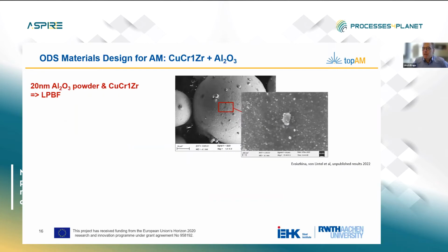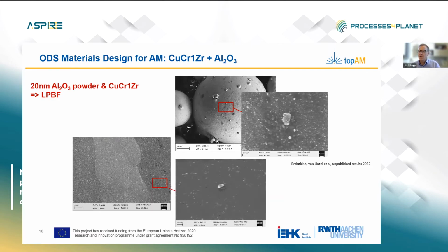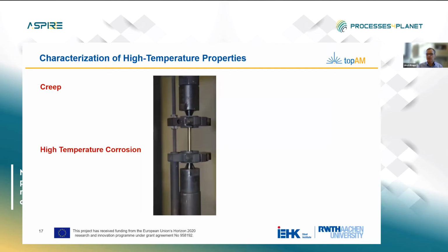We were using a copper chromium zirconium alloy in combination with aluminum oxide nanoparticles, and what you can see here are the nanoparticles on top of the atomized powder. After laser powder bed fusion, what we really can find are particles inside the walls of about 10 to 20 nanometers, and they should be effective in improving the creep properties.